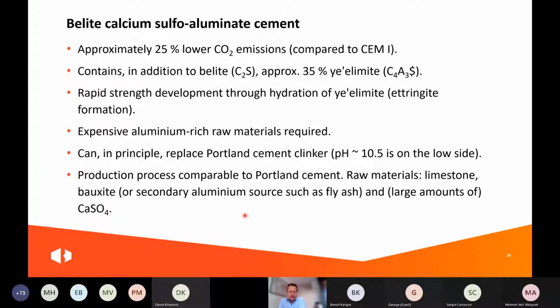Now, a more serious alternative is the belite calcium sulfoaluminate cement. That's also belite, but then the reaction is sped up. The slow reaction of this belite is sped up by adding ye'elimite, which is a combination of calcium, aluminium, and sulfate. And this forms ettringite, and that helps to speed up the hydration of the belite. There are, I must say, several types of this cement under development. So most large cement producers have their own type, and they all differ a little bit. But they all need aluminium as a source.